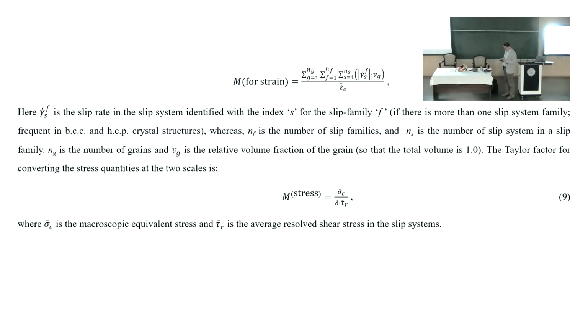This has to be corrected, but the correction is possible by having the small lambda parameter here. Its value is about maximum 1.3, larger than 1. In a recent study, we showed that this effect exists and has to be accounted for. That's another paper—I won't present the details, it's very much theoretical. But for different testing materials, this lambda value is now known and published. So one can correct this Taylor factor to properly account for the energy relation. So anyway, we have two Taylor factors, one for strain, one for stress.